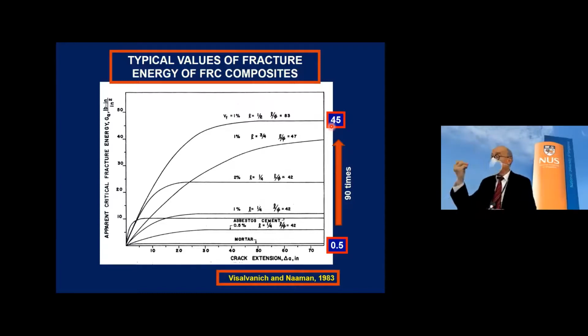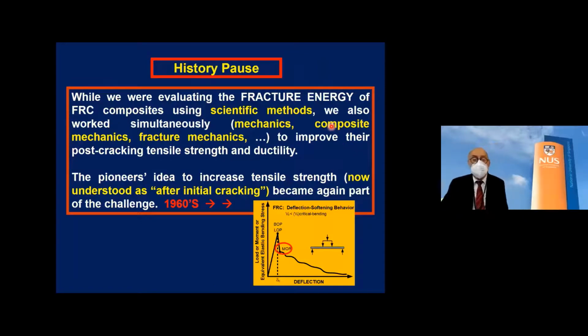But so it's not anymore that the energy is a little thing. The energy became, or fracture energy, or the toughness of the material, became the real key parameter, the key most important parameter. And it has to be so. So I stop here in a history pause. While we were evaluating the fracture energy of FRC composite using scientific method, we also worked simultaneously on the mechanics of the composite, fracture mechanics, strength, post-cracking strength, etc.